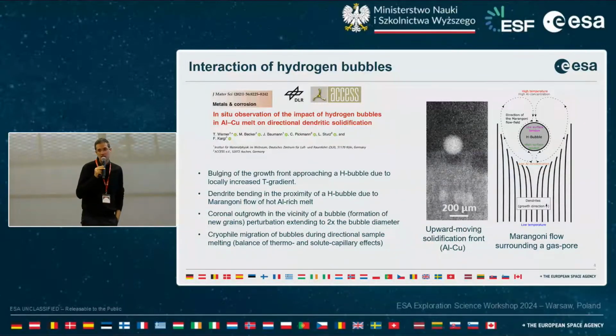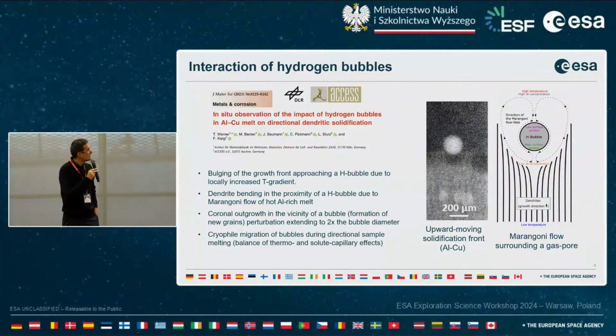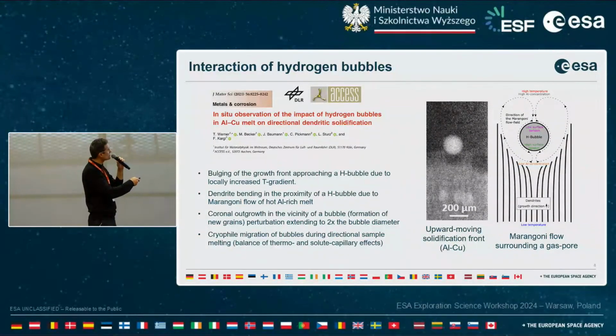It mixes quite well with these elements, and so when you solidify, you will have the formation of dihydrogen bubbles. And this study has been very rich in observations and results when looking at the interaction between the bubbles and the solidification front or within the mushy zone. Here are a few examples of results that have been obtained, such as the bubbles that induce a modification of the local temperature field around the bubble, and it will impact the solidification front.